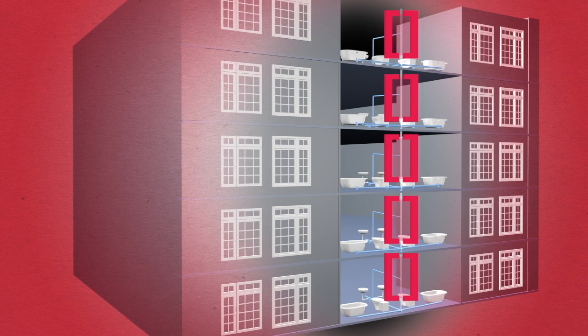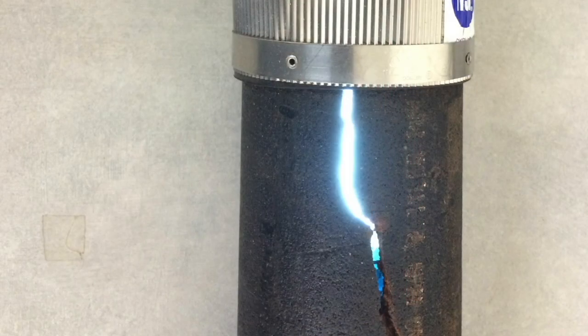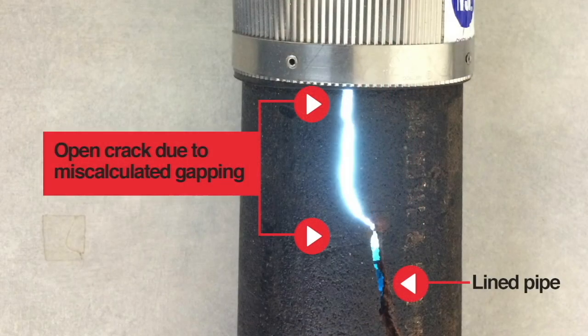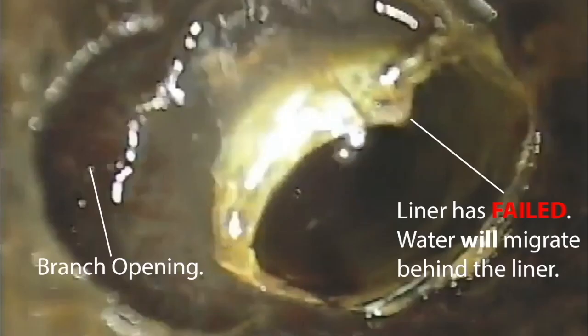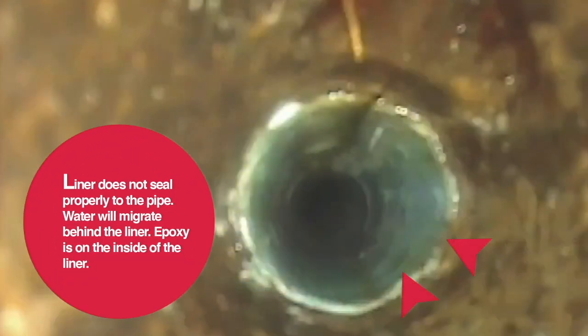The lack of precision in this process can never ensure that the gapped liner is properly covering the fitting joints. These sections of unlined pipe become the future location of leaks and are not covered by any installer or material manufacturer. The greatest flaw in this method is tied to the fact that the slick, impervious coating is installed against the sides of the contaminated pipe.